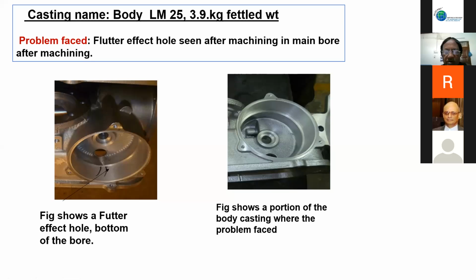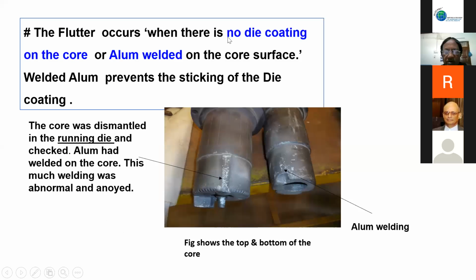Flutter effect comes only when there is no die coat on the core, or when the core is very, very smooth, and if you don't spray this black die coat, you get a hole. Even we can create a flutter and show it to people during the classes. And sometimes when there is no die coat, you have aluminum welded on the core. And this aluminum will not allow the die coat material to stick on it.